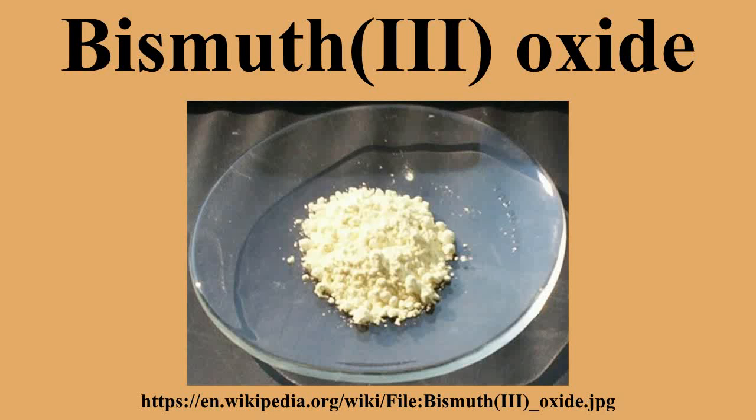MTA sets into a hard filling material when mixed with water. Some resin-based materials also include an HSC with bismuth oxide. Problems have allegedly arisen with bismuth oxide because it is claimed not to be inert at high pH, specifically that it slows the setting of the HSC, but also over time can lose color by exposure to light, a reaction with other materials that may have been used in the tooth treatment, such as sodium hypochlorite.